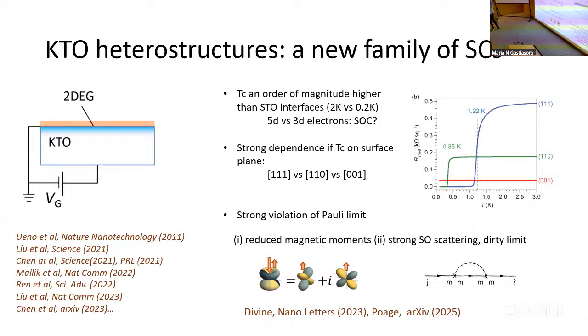So you can think about these supercurrents that are connected to some critical field, but I think the more conservative way of looking at it is you have the Cooper pairs with opposite spin, and now you're putting in a magnetic field, and one of them is going to say, okay, I'm going to orient with the magnetic field because I'm gaining energy, or Zeeman energy. At some point, if that energy is much larger, the pair says, I no longer want to pair, and you break the pairs, and then you go back to the normal state. And these systems break this Pauli limit by a factor of 10.